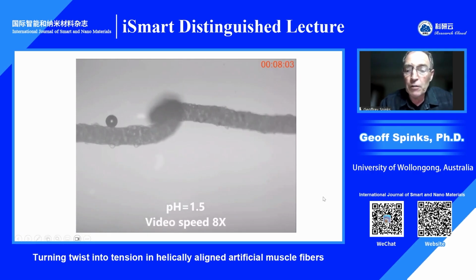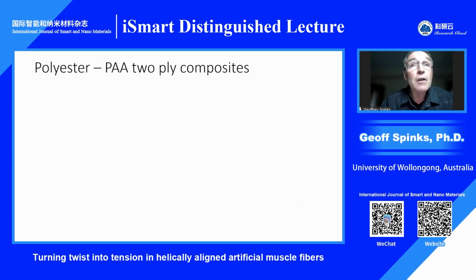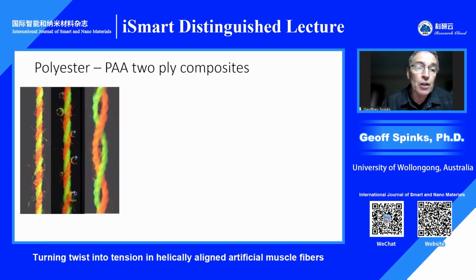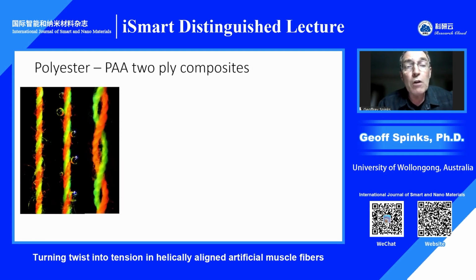We were seeing supercoiling for the very first time in macroscopic sized fibers, proving that it doesn't just happen at the molecular level. The problem was that those polyacrylic acid nanoyarns were very fragile. So I spent some time trying to find a more robust system that we could then do some proper mechanical tests on. So here we're seeing the end result, which is a 2-ply polyester yarn that is incorporating cross-linked polyacrylic acid. On the left is the dry fiber. In the middle is after swelling in an acid solution, and on the right is after free swelling in base.